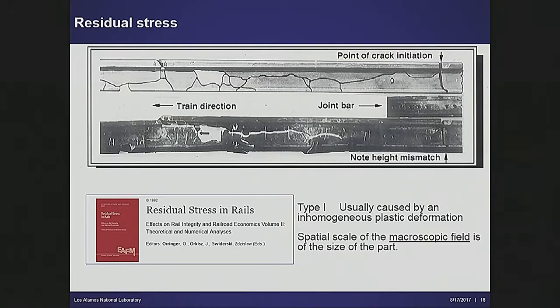And what this shows is a reconstruction of the rail after the fact. What happened was because of the repair that had this height mismatch, the crack that would typically have been impeded at the surface made it down into the web. The web had residual stress in it, and as long as the crack didn't make it there, it wasn't a big deal. But once it made it there, it just peeled apart. So that's why type 1 macro stresses are a really big issue, and it's why people spend a lot of time understanding and modeling them.